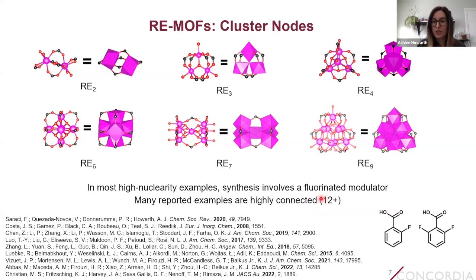But more recently, it's been shown that actually some of the bridging ligands in these cluster nodes are bridging fluoroligands as well as the traditional bridging hydroxyligands. So that's giving more insight into why these fluorinated modulators are required to make these MOFs, because they're actually part of the structural building unit, the fluoro groups, I should say.